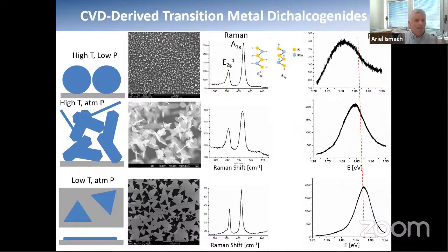So this is basically the simple setup for chemical vapor deposition of TMDs or 2D materials in general that many groups around the world use. And I will explain why these methodologies are not the best to achieve the desired material. As you can see here, you can get vertical flakes or multi-layer areas or very non-homogeneous films. And by the same methodologies, by tuning some parameters, we can end up with totally different materials, from inorganic fullerenes to core-shell metal oxide and metal disulfides, and to one-layer growth domains, as you can see at the bottom of the slide.